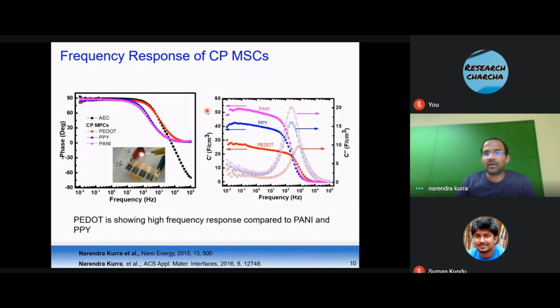And this is also evidenced by further analysis of the impedance, by plotting real capacitance and imaginary capacitance versus frequency, where we can see that the polypyrrole micro supercapacitor has higher capacitance compared to PEDOT, whereas PEDOT operates at a much faster rate compared to the other two conducting polymer based micro supercapacitors because it stores less energy. This is called the maximum of the peak, the frequency you can see. The inverse of frequency is called the relaxation time constant. So this is how we confirm that the relaxation time constant is low, so that you can discharge it fast. This is how the PEDOT micro supercapacitor operates at a faster rate compared to polypyrrole and polyaniline based micro supercapacitors.